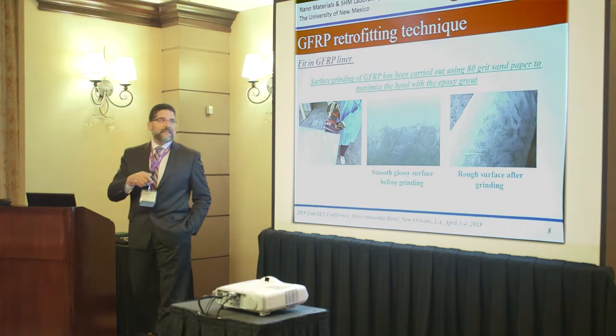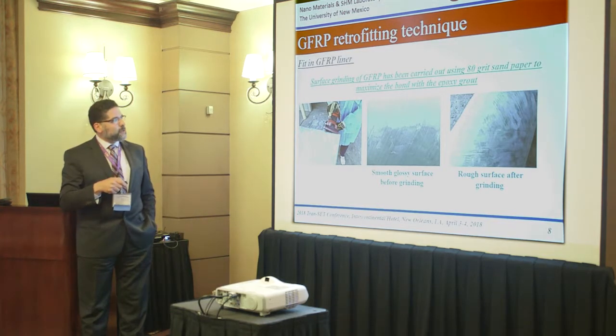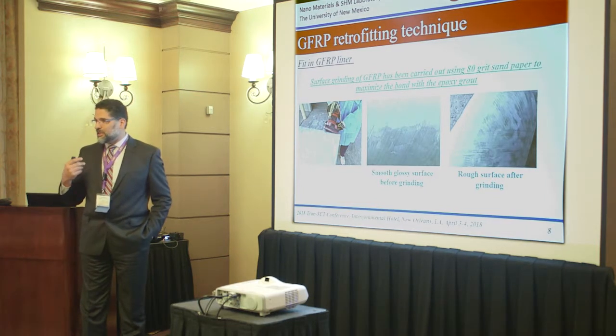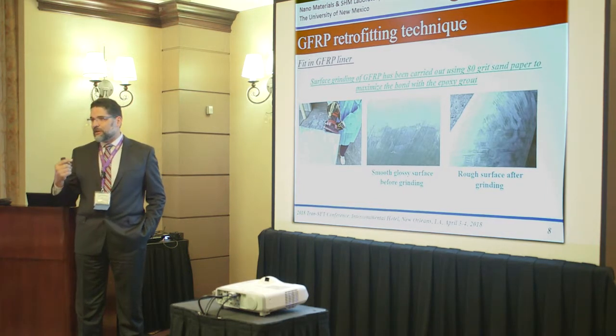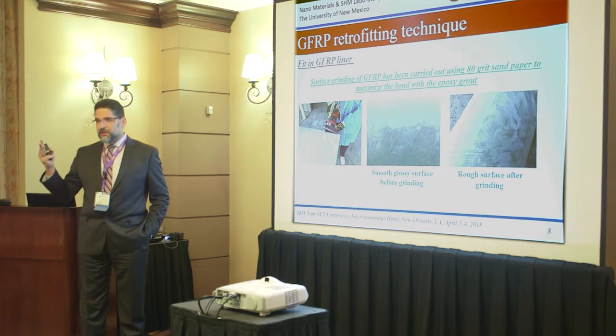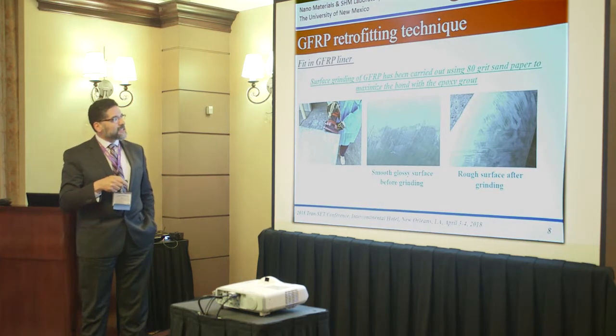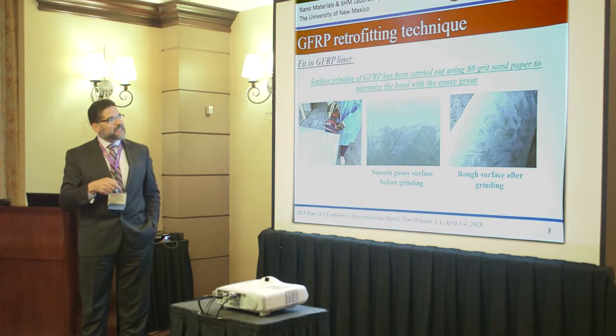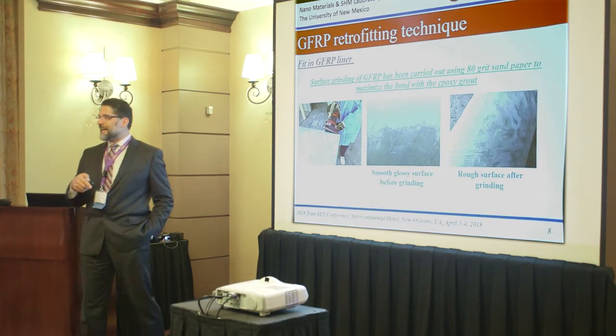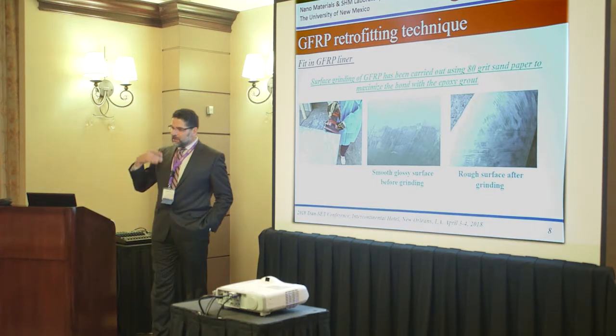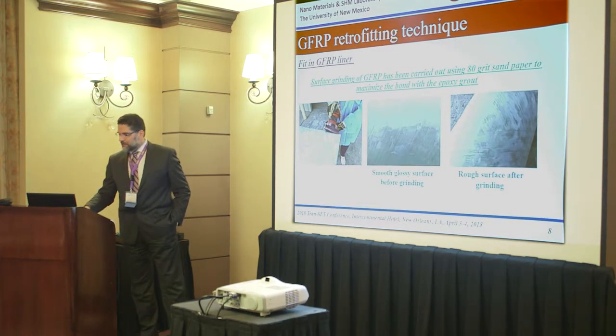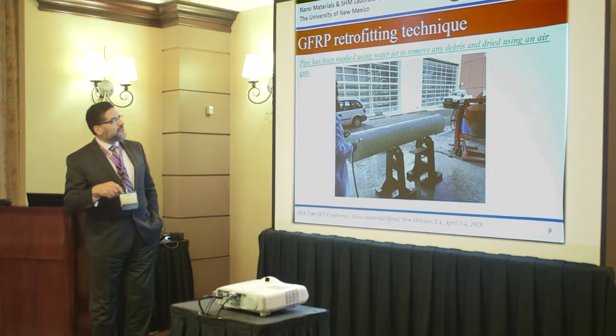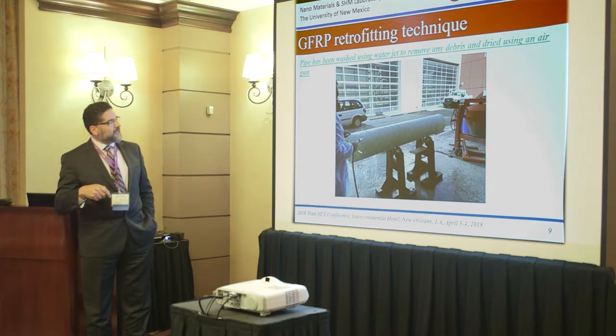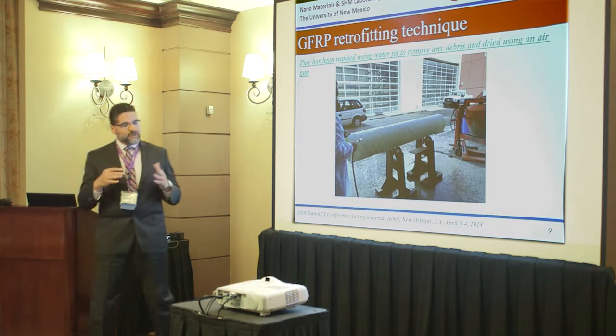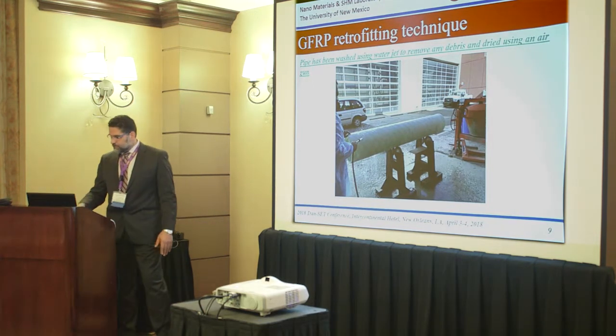Another important thing is we have to work with the producer to identify what type of resin is used with the GFRP, and that's what we did, because there are a few resins usually used with GFRP. Could be epoxy, could be vinyl ester or polyester. In this case, we asked them to use an epoxy because it's got to be the same resin and epoxy material to be used with the grout to maximize the bond between the polymer concrete or grout and the GFRP pipe. So here we are showing that after all the grinding and things, we are cleaning and washing the outer surface with a water jet to be ready for application.